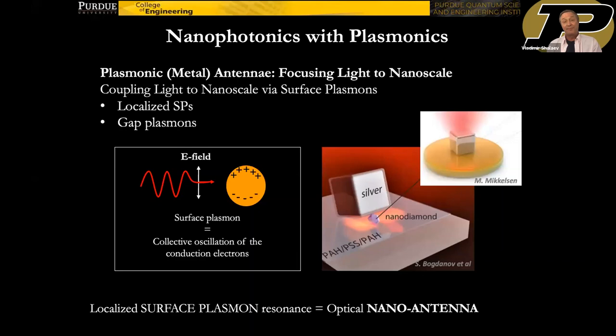It seems that the only feasible way to shrink the size of optical elements to a size comparable to what we have in electronics is to use plasmonics, and specifically localized surface plasmons. I'm giving a couple of examples here. Here you have a small metallic sphere where electrons bounce up and down. That's an example of localized surface plasmons. And perhaps an even more important example of this type of surface plasmon excitation is so-called gap plasmons, when the electromagnetic excitation is confined to a dielectric gap between two metallic structures. The gap could be really small, only a few nanometers, and the whole electromagnetic mode could be confined to this dielectric gap. So that's the idea: to take the speed of optics and use plasmonics to shrink as much as possible the volume of the electromagnetic mode.